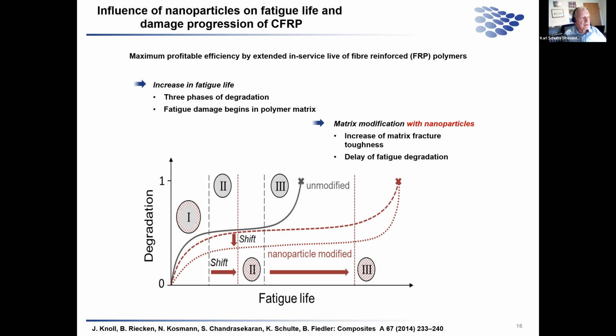During damage development, the reduction in stiffness, or this degradation, is due to the fact that we have damage, we have cracks, and we have a transfer of the load away from the damaged area into the intact area. That means the intact area is higher loaded, we have a higher strain there, and that means we have a reduction in stiffness - this is what we put together as the degradation.